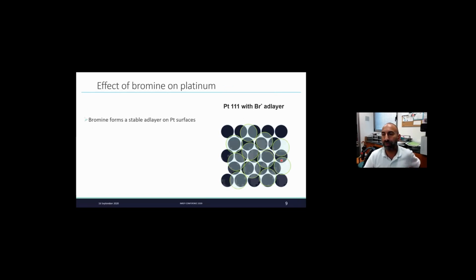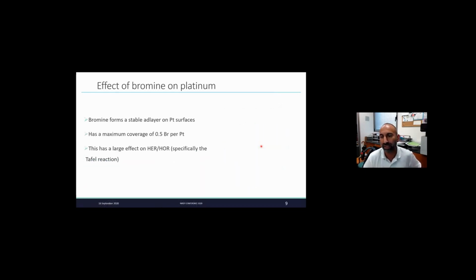So the problem with bromine is that it's sticking on the platinum. You have here the black spots, which are the platinum atoms on the platinum 111 surface, with some bromine adlayer on top of it. So the bromine are the large green spheres. So the bromine is sticking to the surface of the platinum. And then when it's there, the platinum should do the reaction, the dihydrogen splitting.